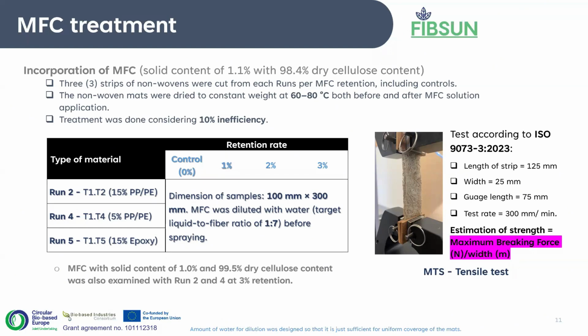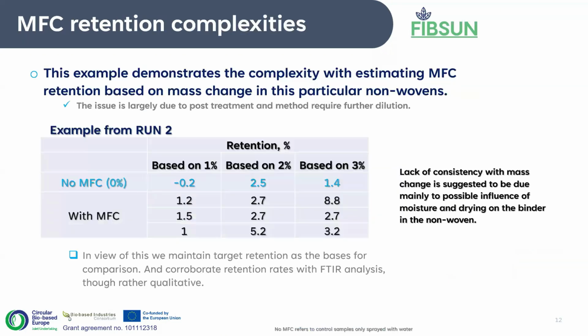So looking back at the batch of nonwoven we've worked with, again, the 3 rounds of nonwoven, we then tested target retention rates of 1%, 2%, and 3%. In this case, we incorporated MFC into these nonwovens by spraying after dilution, based on the mass of the nonwoven, to have a solution target of 1:7, which is 1 gram to 7 grams of solution. And then again, we examined the tensile properties of this nonwoven.